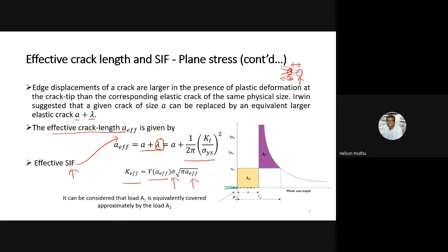Why did we extend the crack by lambda? See here on the bottom end of the slide, there is a crack of length A, elastic, perfectly plastic material. So here you have the physical tip, and we have extended the crack by lambda, the mathematical tip. How is it possible? Because when you extend the crack by lambda, if you were to solve this problem using LEFM, naturally you would have got this as a solution: singular stress, an asymptotic stress field. So that has been the solution. But because it is elastic, perfectly plastic material, in this region you are going to have sigma ys. So all the stress is going to be sigma ys.